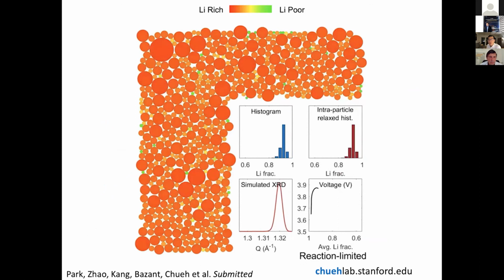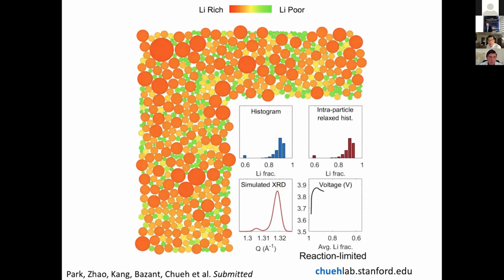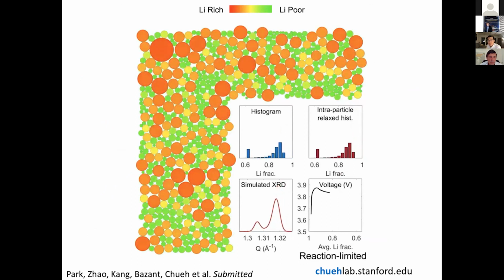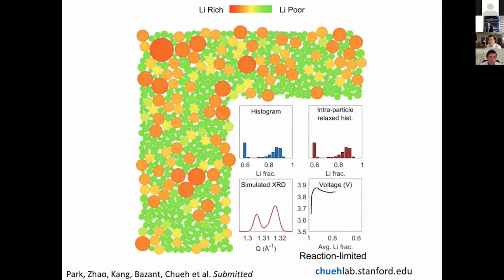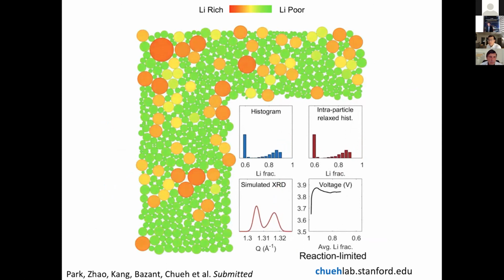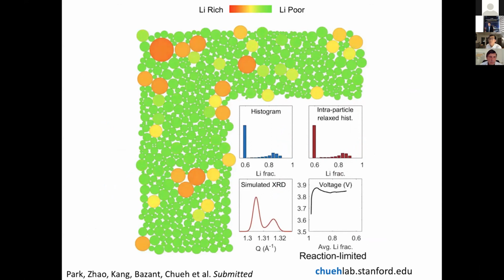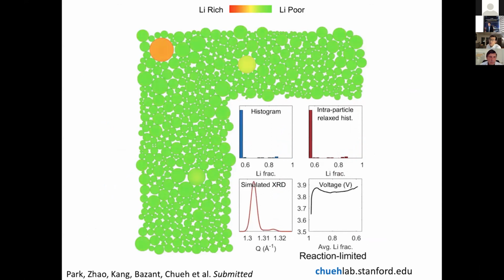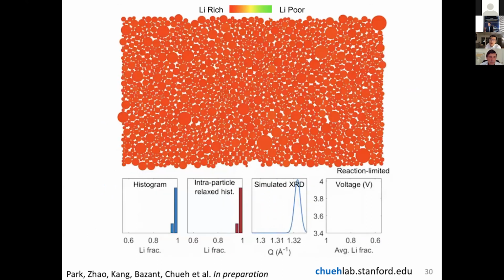So this is a movie of the same phenomena, but now you don't see the diffusion front anymore. You see the effect where select particles are receiving lithium preferentially as you remove lithium, but then when you put lithium back in, it's very uniform. So this is yet another example of autocatalysis.